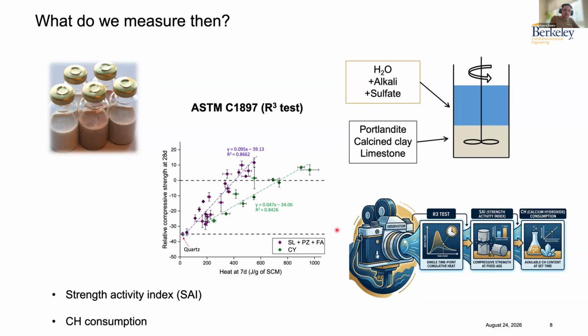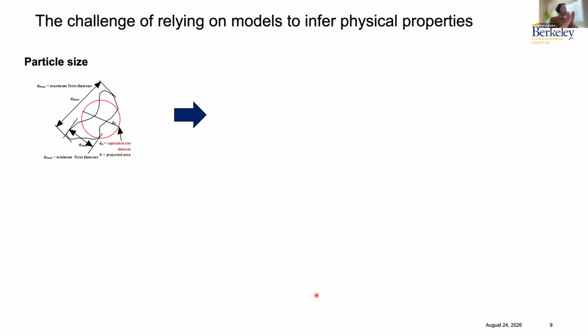So we take this snapshot in order to capture what's going on at a certain period of time. But it's important to keep in mind that this snapshot is not a representation of the reactivity. Actually, the reactivity considers this evolution over time, which we capture with the R3 test. It's just that that's not part of the value to be reported within the standard test method.